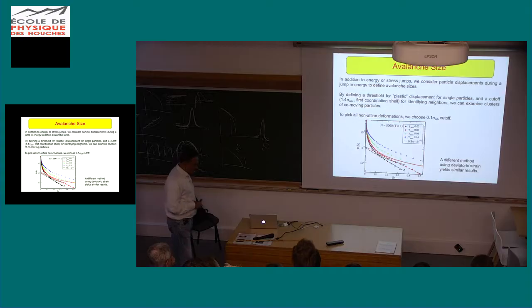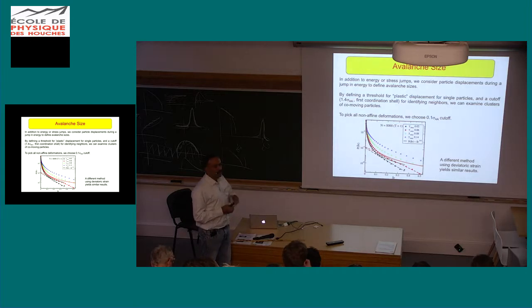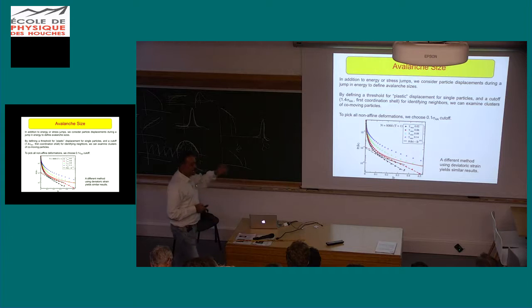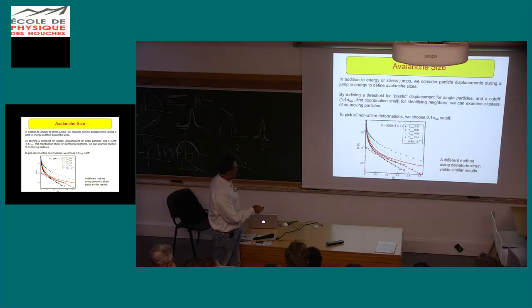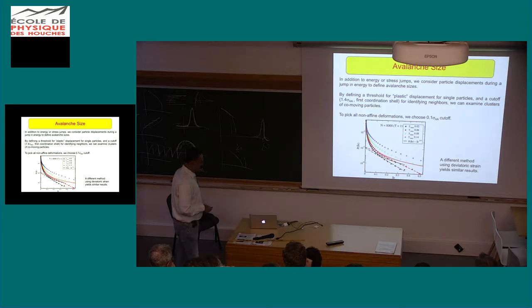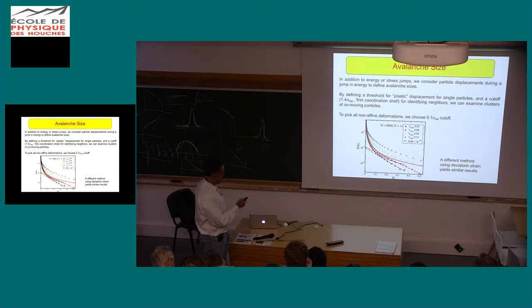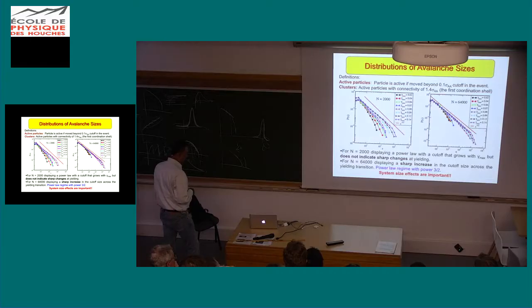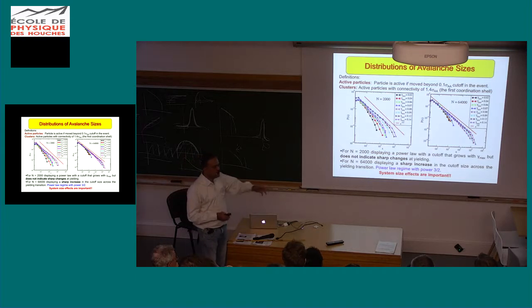Okay, so how do we identify avalanches? In addition to looking at energy drops and stress drops, we also try to identify the regions in space and their sizes where plastic deformation occurs. We do this by looking at the distribution of displacements of particles when one of these energy drops occurs. And we find this to have a power law small value region followed by an exponential tail, and there's some argument for why this should be the case. I won't say it right now, but we look at the crossover from the power law to the exponential to define a threshold, and any displacement that's bigger than the threshold is a particle that has moved within a plastic core, and the rest are elastically displaced particles. By this process we identify clusters of particles that moved in an avalanche, and we look at the distributions of their sizes, and here they are.